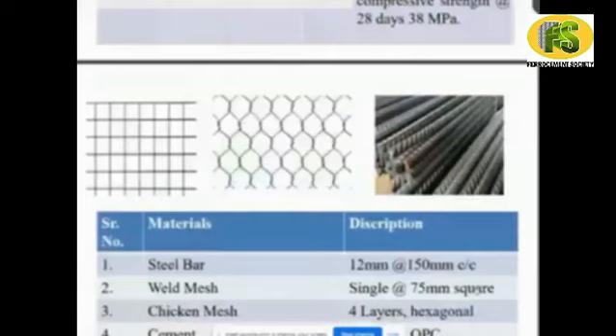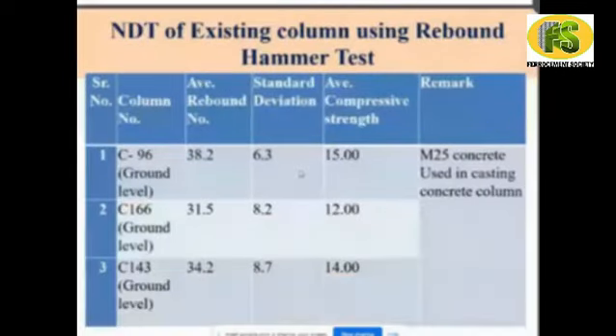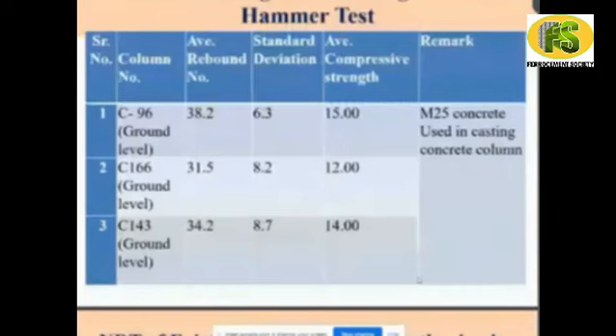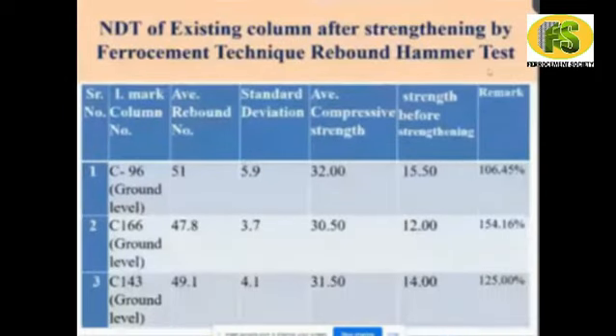As usual, in ferrocement, we have used the vertical bars, then square mesh, and then chicken mesh. No issue for that. Then this is the NDT of the existing column using the rebound hammer. I have shown the comparison. For C96 at ground level, the average rebound number is 38.2, the standard deviation is 6.3, and the average compressive strength is 15. Actually, we designed for M25, and these are the results: 15, 12, and 14. This is at the ground level. Then NDT of the existing column after strengthening by the ferrocement technique.